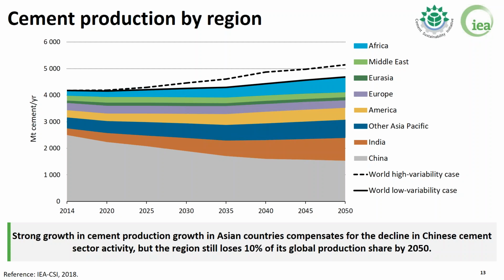What you can see in the depicted regional breakdown for the low variability case is that even if we are expecting a slowdown in the activity of the cement sector in China in the long term, as you see in gray at the bottom, still the whole Asia region keeps a quite similar overall level of cement production over time, because the slowdown in China is compensated with stronger growth in India and other Asia Pacific countries, specifically India being the main contributor. But also you can see that there are other important growing regions such as Africa and especially Latin America.